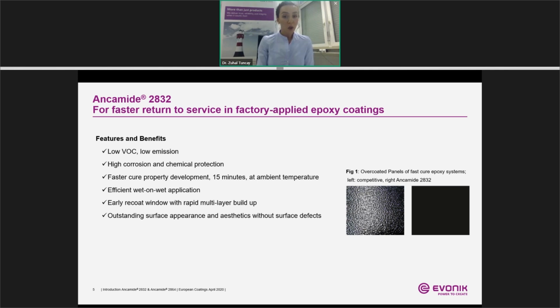2832 is high in solid and exhibits low emission. It can be used as primer or intermediate coat. It provides high corrosion and chemical protection, and it shows very fast property development. After 15 minutes at ambient temperature, the system is dry to touch and ready to receive the top coat. That rapid overcoatability makes 2832 an ideal product for wet-on-wet application.